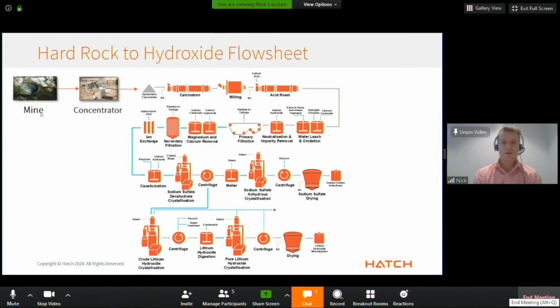So let's look at what that flow sheet actually looks like. For the hard rock processes, we mine it, produce a concentrate. We heat that concentrate up to 1100 degrees, mix it with sulfuric acid and bake it at 250 degrees. And then it's the more boring hydrometallurgical aspect where we leach it, remove the impurities, and produce our lithium carbonate crystals, or lithium hydroxide in this case.